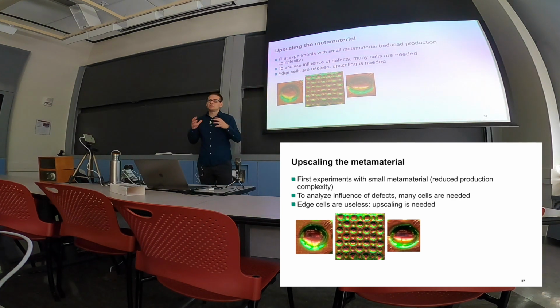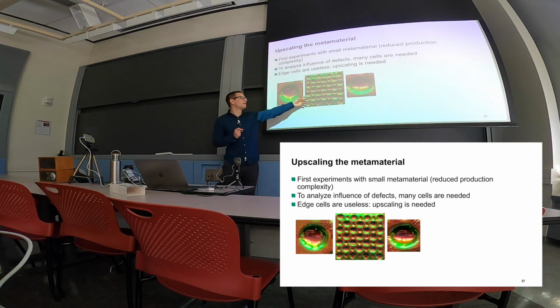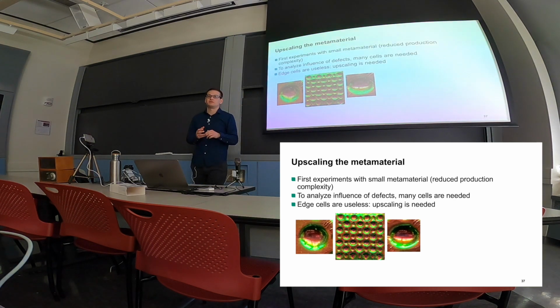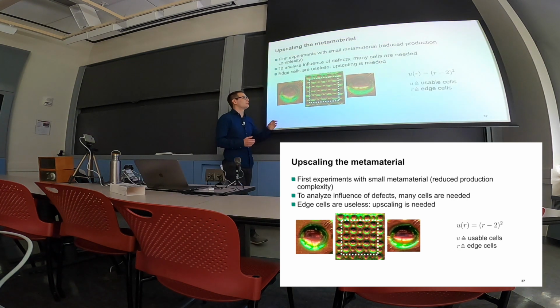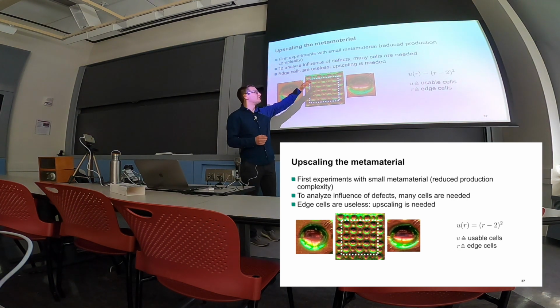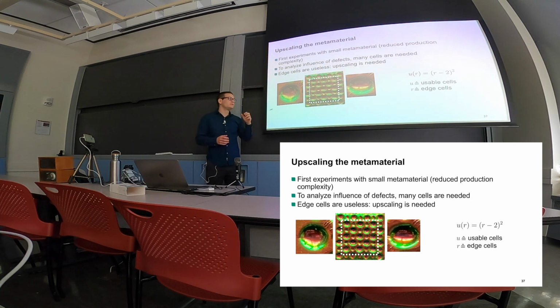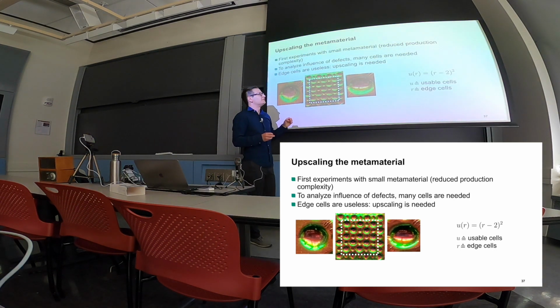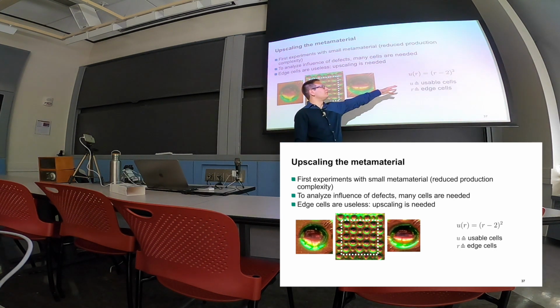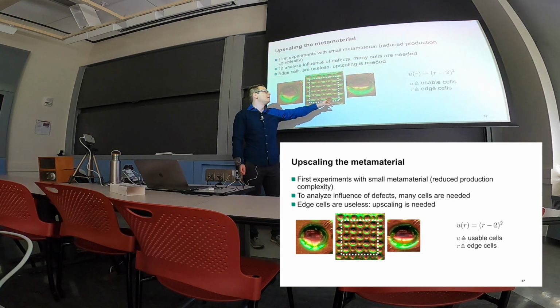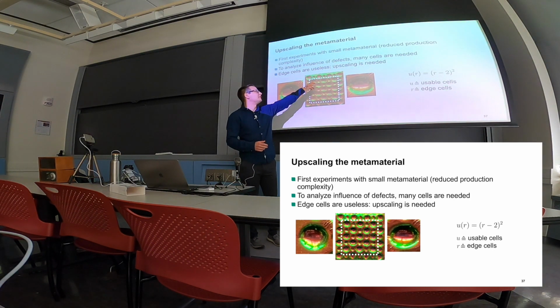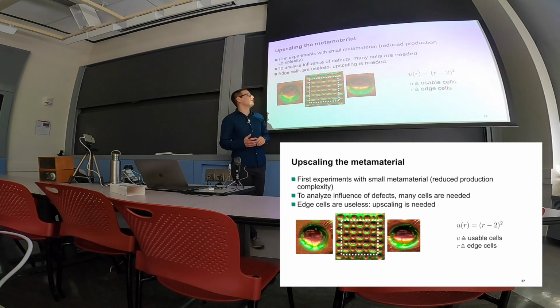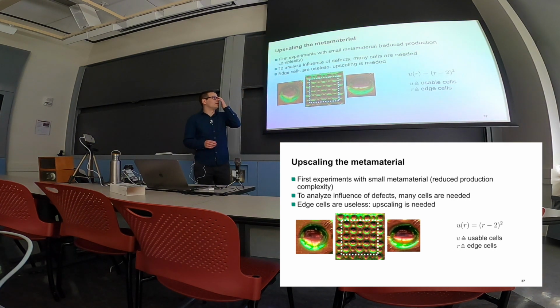So the cells on the edges are influenced very much by the walls of the metamaterial, because they are a little bit thicker than the walls on the inside, and therefore deformation doesn't take place in those cells anymore. So I had the problem that I ended up with an even smaller network that I could use for analyzing, because the outside cells were influenced too much by the edge of the whole metamaterial. And so the usable cells were basically all cells in one row, minus 2, to the power of 2, and this ended up in only, let's say, 9 usable cells for that object over here, which is not that much.